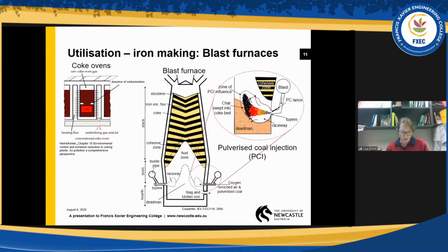You don't get gas flowing through your bed, you don't get reduction. Issues for both coke and PCI is chemistry. If you have too much potassium in there, potassium attacks the strength of the coke and breaks it down. So you will actually get that reduction in the permeability of your bed. Potassium also attacks the refractories inside the blast furnace. So too much potassium and the coal is not suitable for steel making or for iron making.